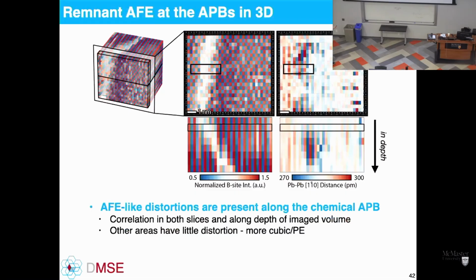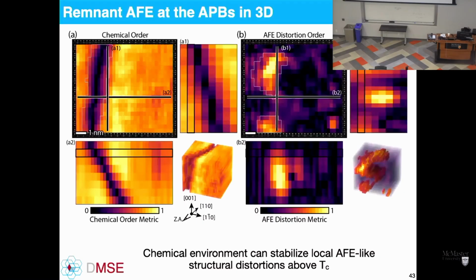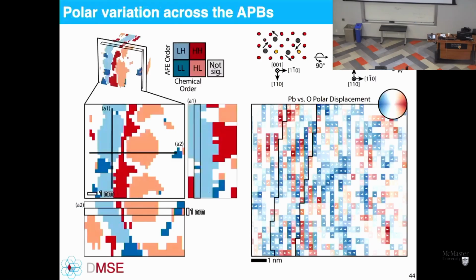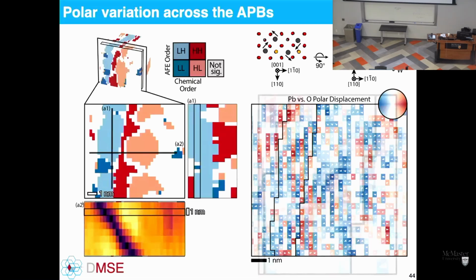We can reconstruct the thing in 3 dimensions to find that what we're really seeing occurring at the inclined boundary is not just chemical change, but also property change, meaning we have a dipole alignment of that antiferroelectric structure on that plane as well. So we seem to have local chemistry that is stabilizing that antiferroelectric distortion. It's shown in a little bit better, clearer detail of the 3D volumes overlapping between the antiphase boundary and that chemical disorder. And finally, we can map out those two and do some statistics of where our polar order is and where that boundary is, and the antiferroelectric aligns right at that position.